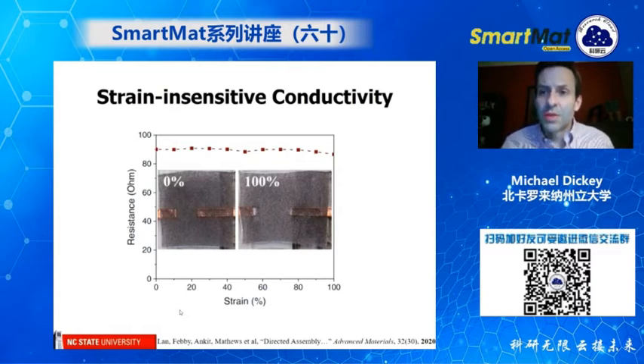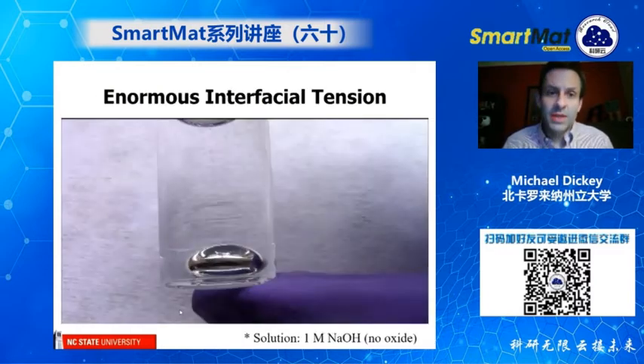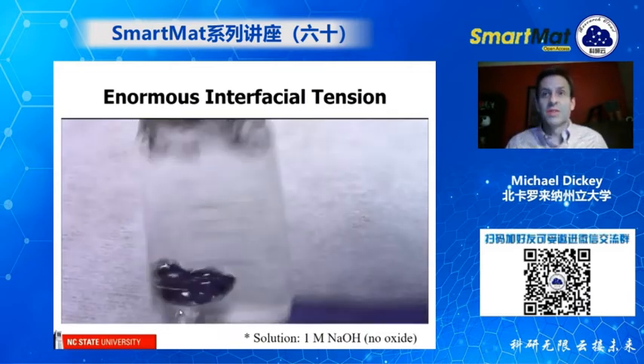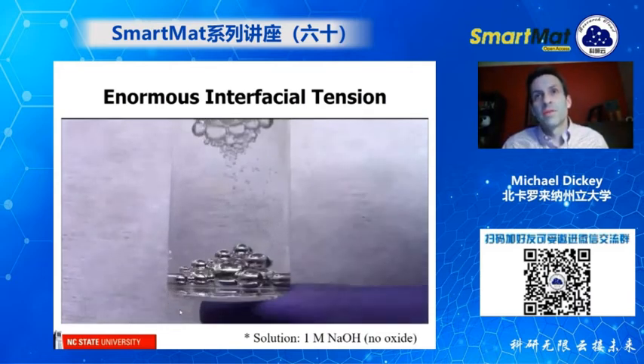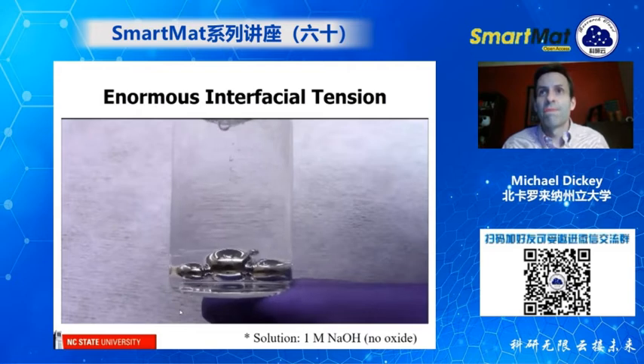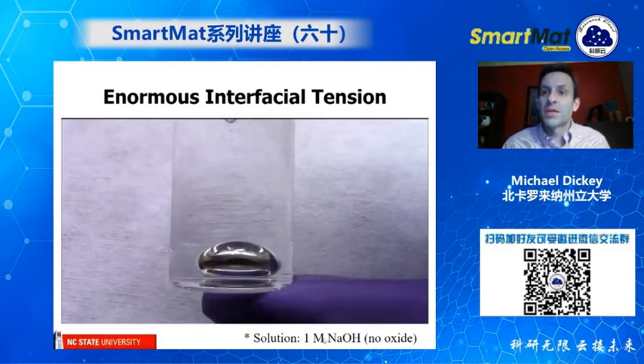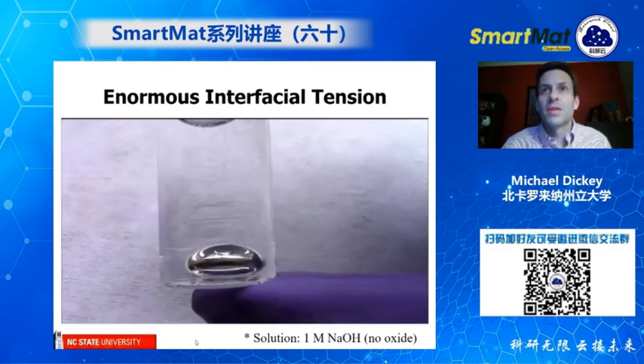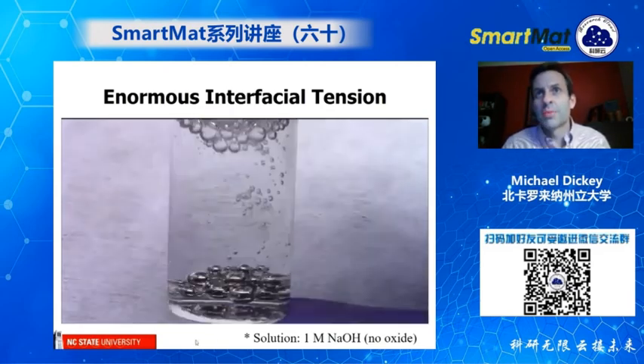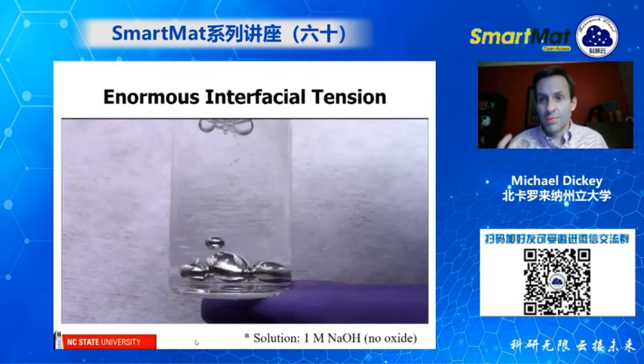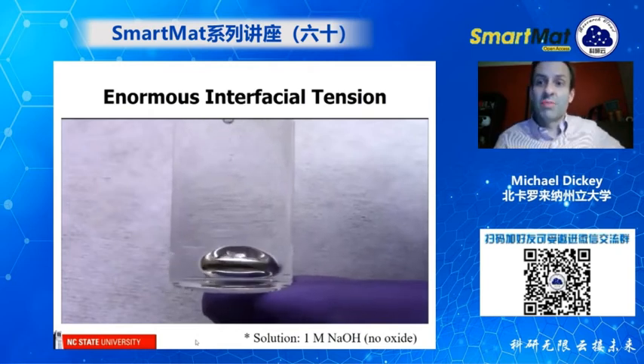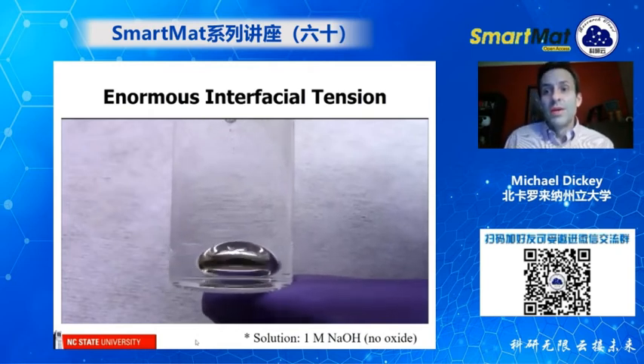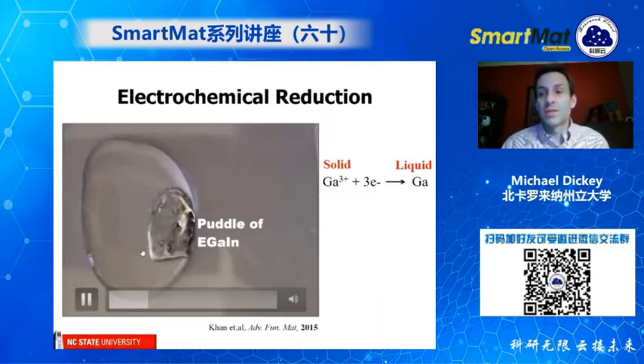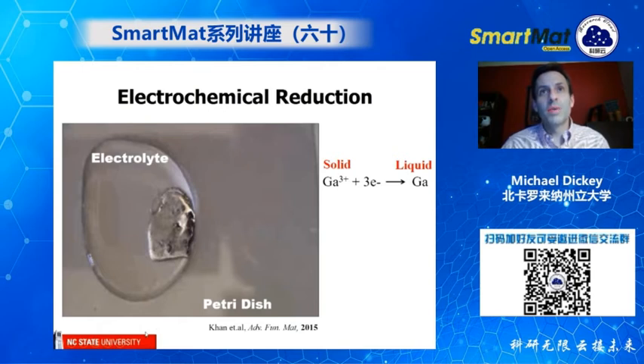And that is that liquid metals, if you remove the oxide layer, actually have enormous surface tension. So this is the liquid metal inside of a vial of sodium hydroxide. The sodium hydroxide has a very high pH, and it will remove the oxide layer. So when you shake this, it will break into droplets, but it'll very quickly go back into one droplet because it's trying to minimize its surface energy. So with the oxide, this is the liquid metal sitting in some salt water, it will hold its shape until you remove it.